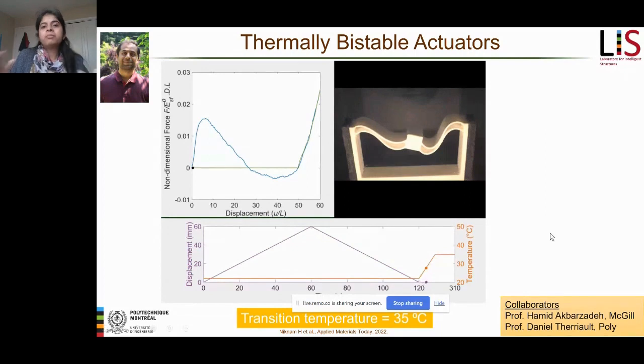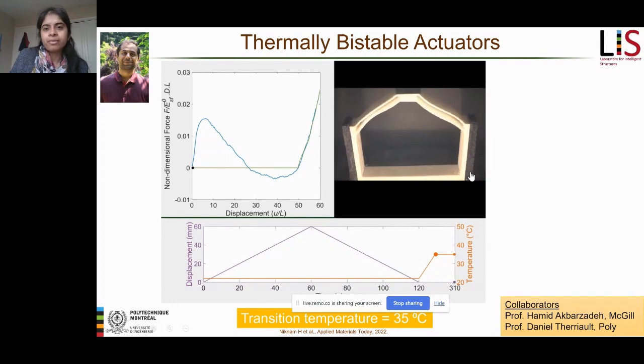In this case, the temperature of transition depends again on the thickness or the width of this carbon fiber material and these struts. So you see now we are at 35 degrees Celsius, and our structure is going to go back to its original shape in a bit. So we did achieve actuation in this case using stronger, off-the-shelf materials, and we didn't need to go into smart materials. So this was one of the very interesting works that we did here at Polytechnique.